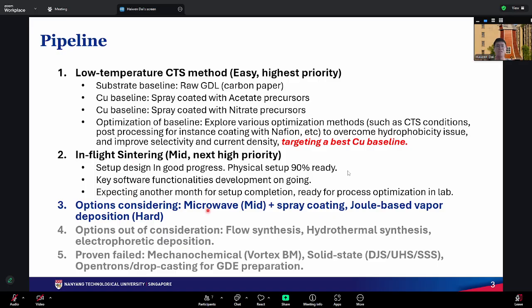We also have some other considerations in mind. Currently there is a new microwave synthesis, which is not solid state microwave synthesis but a wet chemistry microwave synthesis. We will be engaging the suppliers tomorrow and asking for their potential recipes, connections, and application notes. And there is a more conventional method, spray coating plus Joule-based vapor deposition. I had a chat with Chenghua. However, once we introduce vapor deposition, the elemental ratio control will not be directly relevant to the precursor we put in. That is the key here. So according to the difficulty and ease of achievement, we rank these as 1, 2, 3, 4 different options.